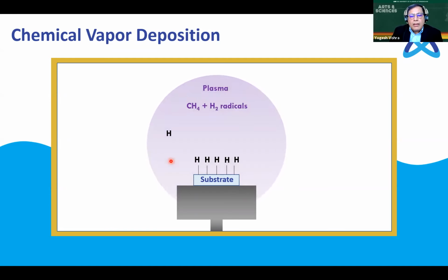So imagine that you have a hydrogen atom in the plasma come in and extract another hydrogen, forming a hydrogen molecule. That leaves us a vacancy here, which can be filled either by a hydrogen or by our desired species, which is carbon in this case. So we have a carbon species which attaches. You can think about it this way: repeating this process, we can have a layer of carbon attached to the surface of the substrate.